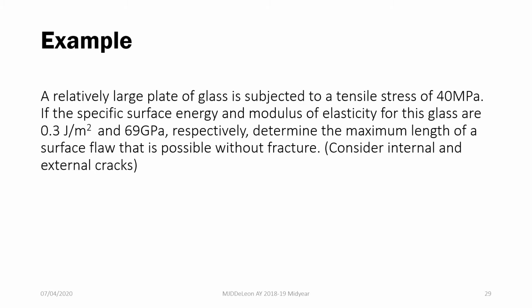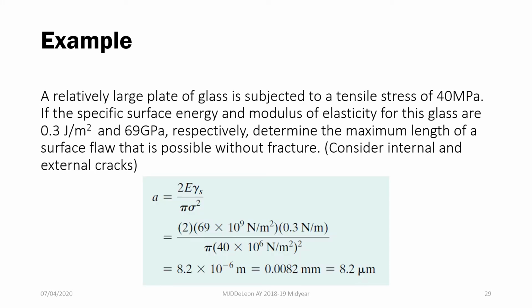So kanina, you have an equation relating your critical stress and your elastic modulus, your surface energy, and your length of the crack. Using that equation, we can manipulate that one. So we get a, or yung crack length na unknown sa atin. We have a is equal to 2 times E gamma S over pi sigma squared. So, lalagay natin lahat nung ating given. E, or our elastic modulus, is 69 gigapascals. Our surface energy is 0.3 joules per meter squared. And your tensile stress is 40 MPa. So, we're looking for the length of the crack that can withstand this stress without fracture.